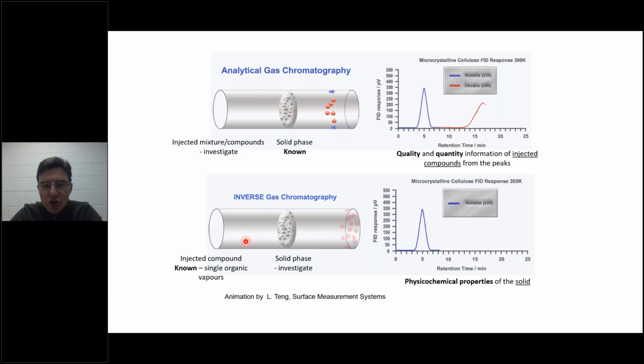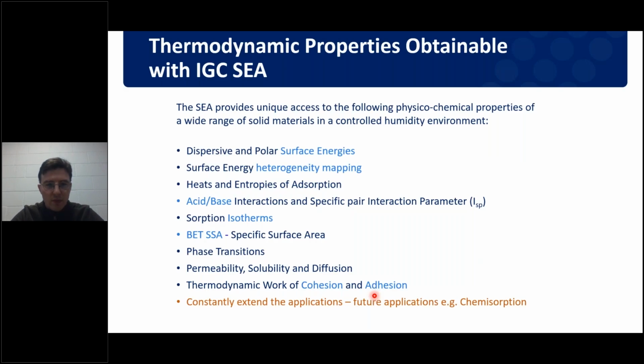Now, if I change the concentration of this probe I am injecting, I am going to get very slightly different profiles of my retention curve. And it's from these slight changes from different concentrations that I get the properties of the surface. So I can repeat this with a number of different probes, put all of that information together, and then I can get some physicochemical properties of that solid and of that surface.